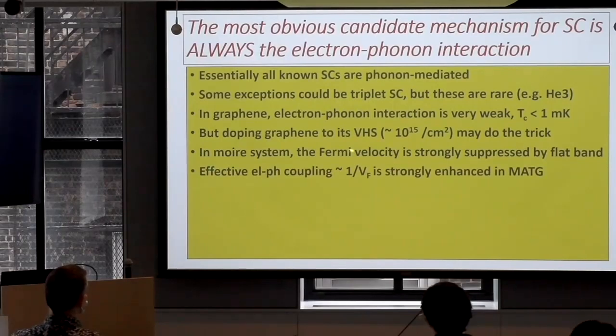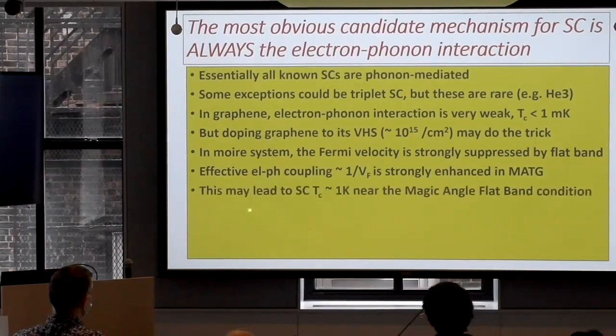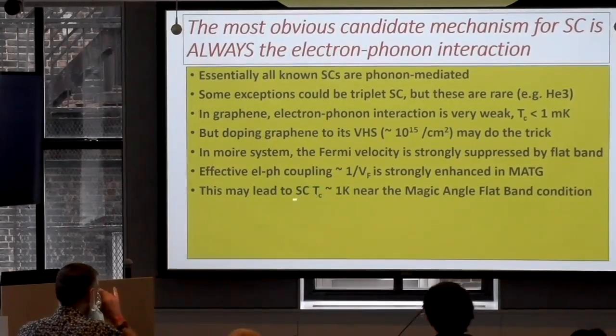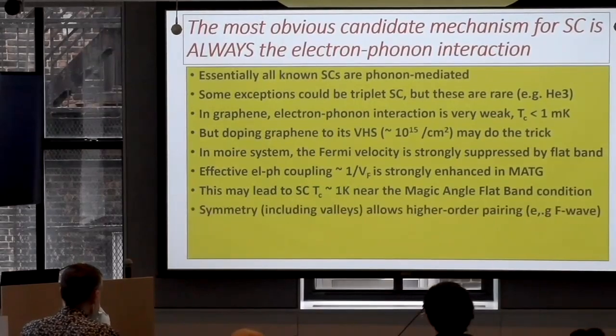So if you have a Fermi velocity lower by a factor of 100, electron-phonon coupling will be a factor of 100 higher. And in fact, Fermi velocity is zero at the magic angle, so this coupling is going to go to infinity. Of course, the theory would not apply there. And if you just do a BCS theory, just the BCS formula, this will immediately give you a TC of 1K. This is the basic idea, okay?